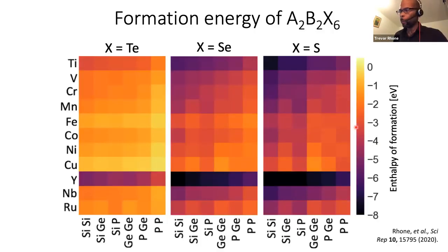Okay. So we're not only caring about magnetic properties, we also want to make this thing in a lab eventually. So we also care about chemical stability. And we attempt to estimate chemical stability by plotting the formation energy. And that's shown here, for the same scheme: A site substitution for the vertical axis, B site substitution for the horizontal axis, for different X values, tellurium, selenium, sulfur. Now the color is the formation energy, where the darker color means the crystal structure tends to be more chemically stable. And there's a clear pattern now in the data going from the left to the right of transition metals.